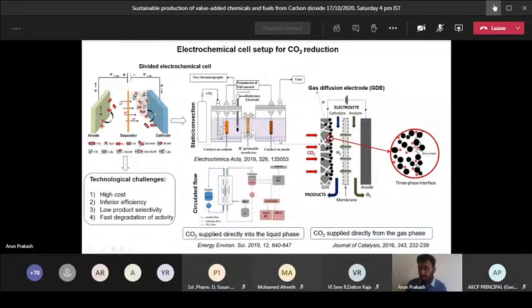So the diffusion and concentration profiles are very important, and the boundary layer also plays a major role. If you have a smooth electrode surface, the boundary layer will be different. If you have a curved and porous electrode, then the boundary layer may be different. You have to consider all these, and depending on that, the local pH may change. So we have to consider the electrode, reference electrode, counter electrode, and electrolyte. What counter ions do you introduce into your electrolyte, and what local pH changes happen during the CO2 reduction?